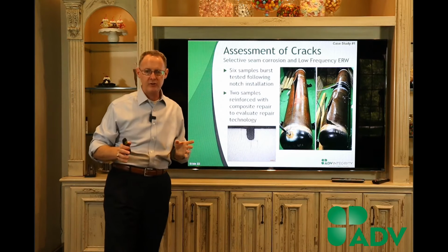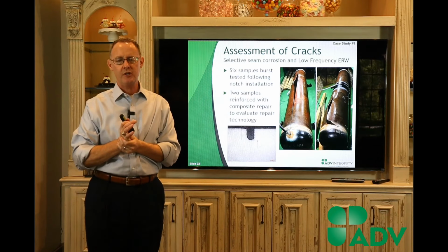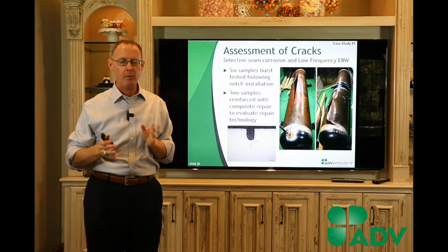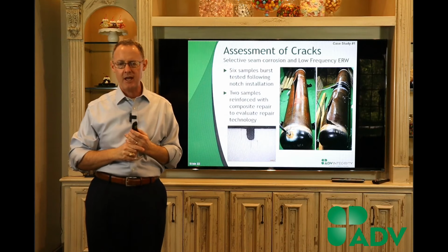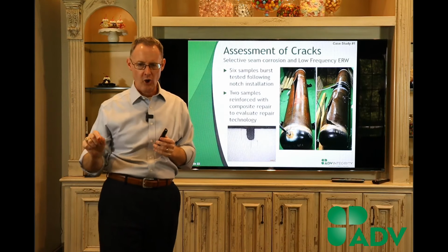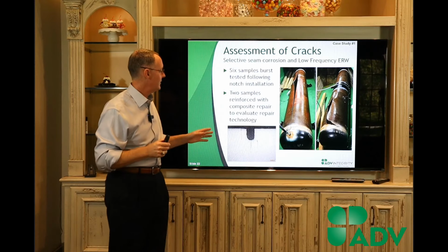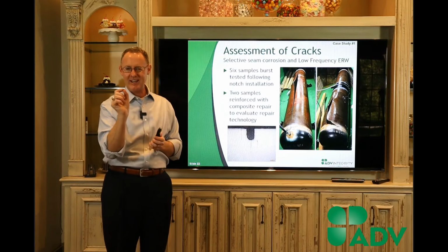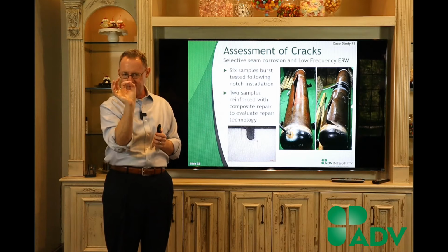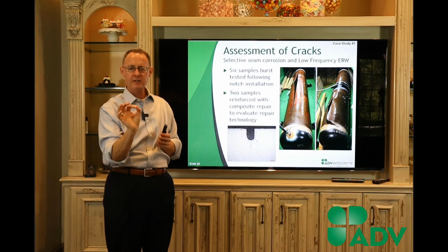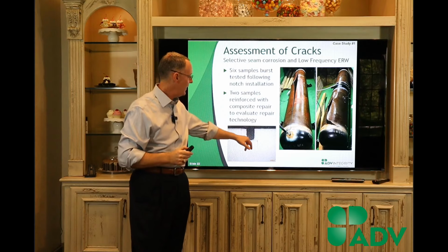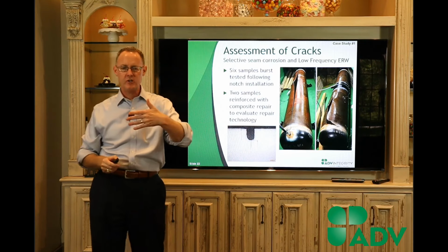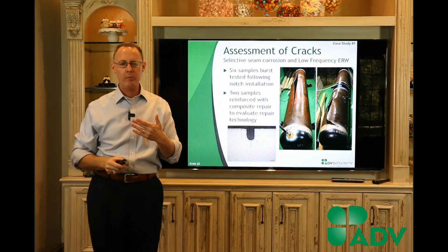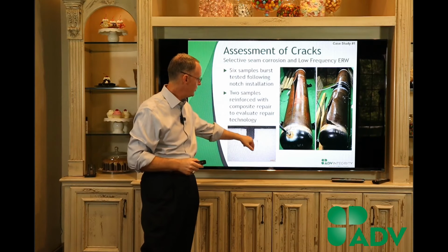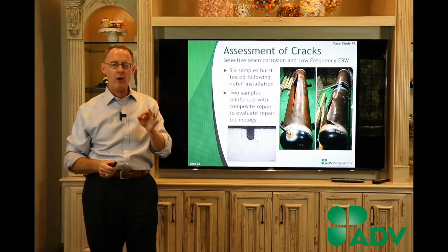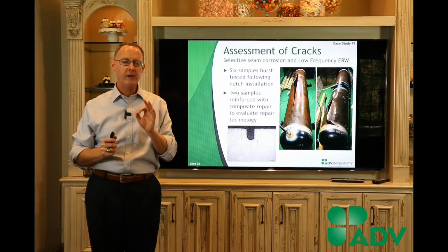And I'll admit, when I first started doing a lot of this work 6-7 years ago, I didn't fully appreciate it. I remember Ted Anderson and I having a little discussion about that time. He's like, look, Chris, notches are not cracks. And when you send the electrode in there, this thing is like 10,000ths of an inch wide. It's very, very narrow. We try to make it relatively sharp at the bottom, but you push it in, and then you take a cross section of it, you put it under a microscope, that is not sharp at all. But when you cycle it, what you notice is we get that crack. That crack is sharp. So now if we did a burst test, okay, we're really testing a crack.